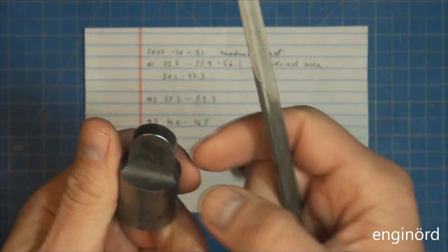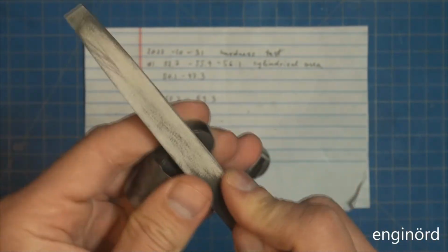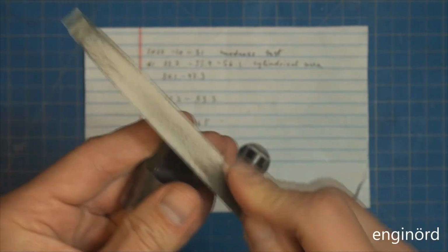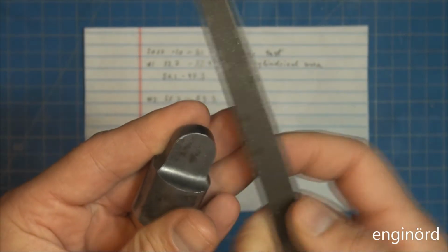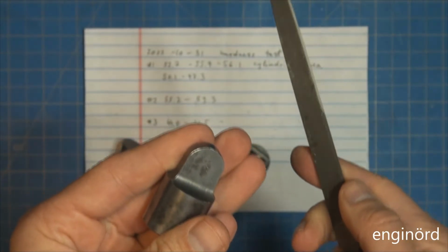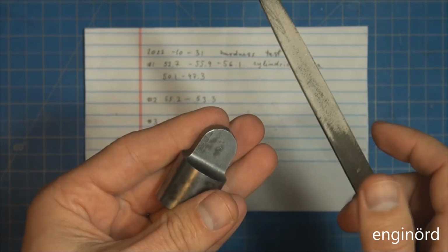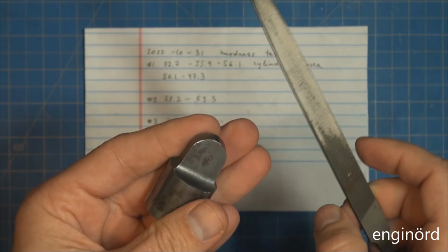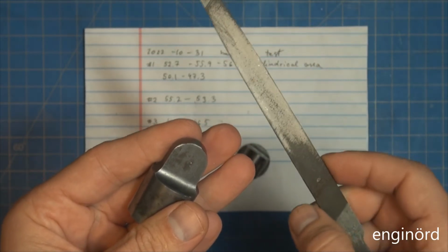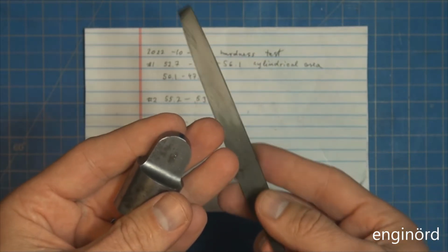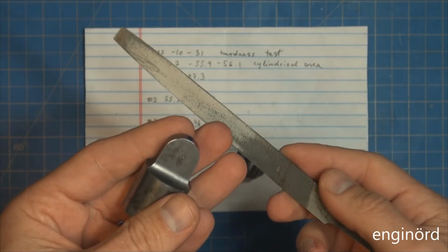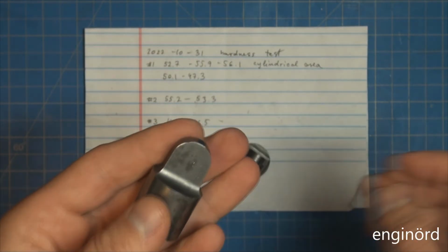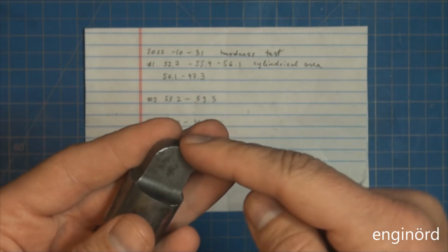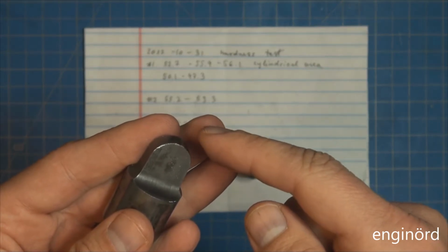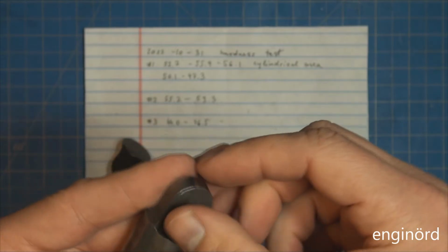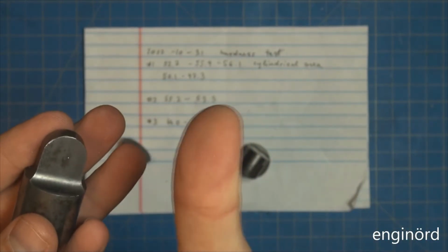As far as hardness, the file is gonna cut it. So whenever you see someone testing hardness with a file, it's kind of a low standard of testing hardness, because the file can be 62, 65 or higher hardness. Some of these files, if you drop them, they're gonna shatter because they're through hardened. They are like glass. And you can see in this case, this is proven that it's higher than 50 Rockwell, and yet it's cutting it. There are metal chips being generated.